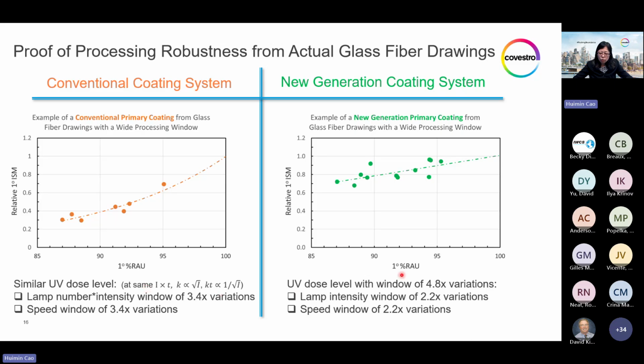And in clear contrast, the new generation primary coating shows a very flat, linear curve, almost plateau, with modulus buildup at 90% of the cure already reaching 80% of the modulus, and this way ensuring a very stable coating property profile, and as a result, very robust fiber performance in the wide window of processing conditions and also after post-cure.